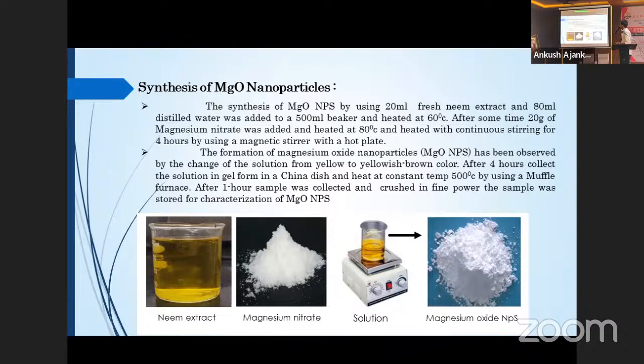For the synthesis of magnesium oxide nanoparticles, 20 ml of fresh neem leaves extract and 80 ml of distilled water were added to a 500 ml beaker and heated to 60 degrees Celsius. After some time, 20 grams of magnesium nitrate was added to the solution and heated at 80 degrees Celsius for 4 hours using a continuous stirrer and hot plate. The formation of magnesium oxide nanoparticles was observed by the solution color changing from yellow to yellowish brown.